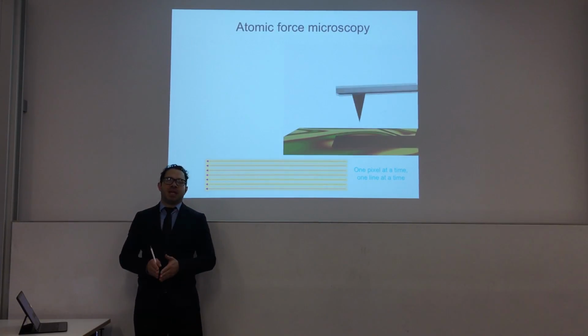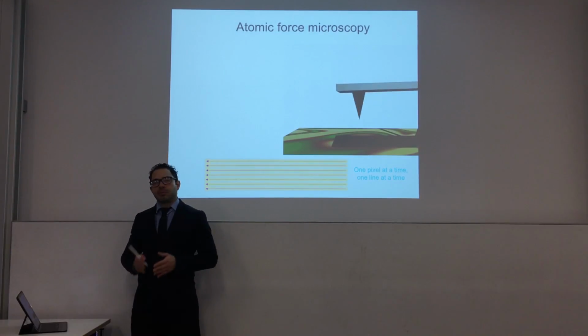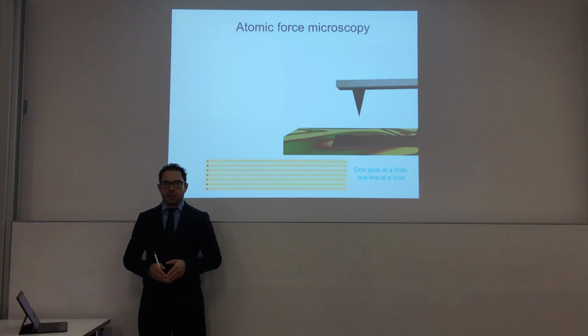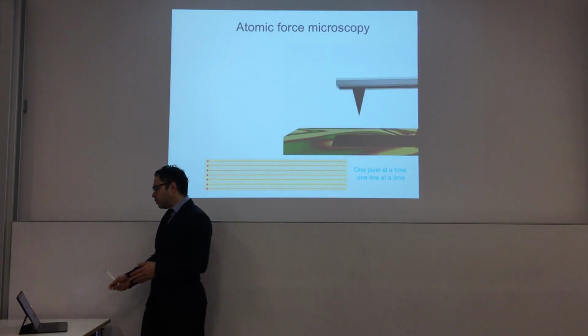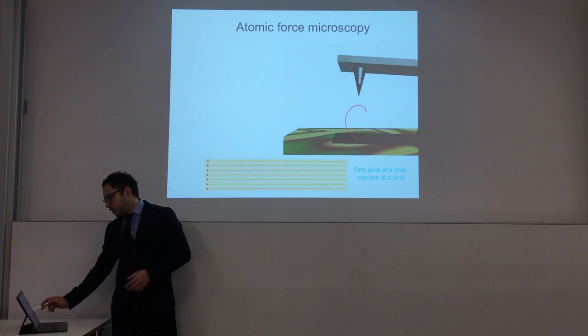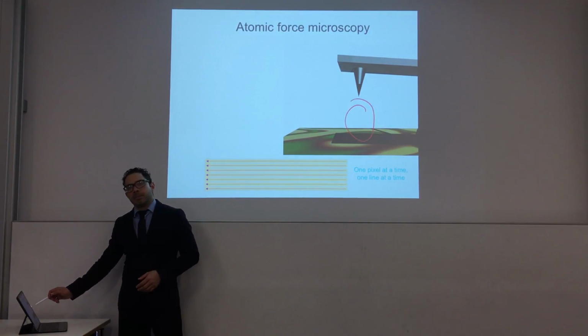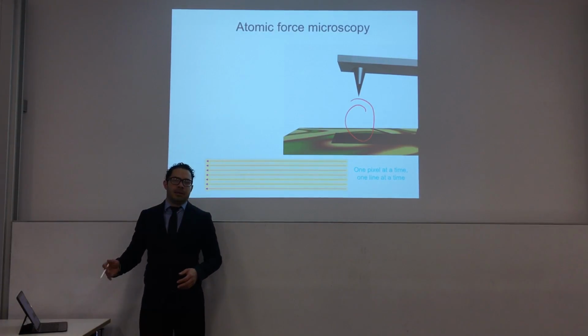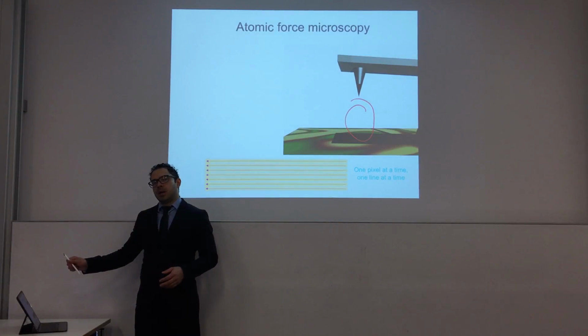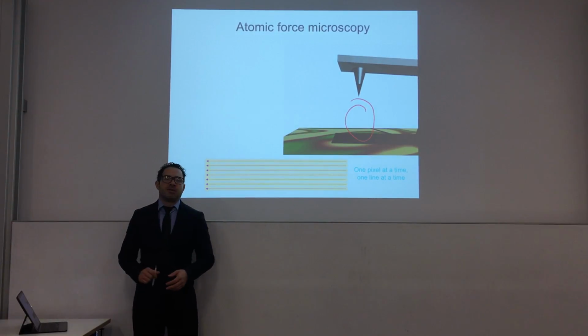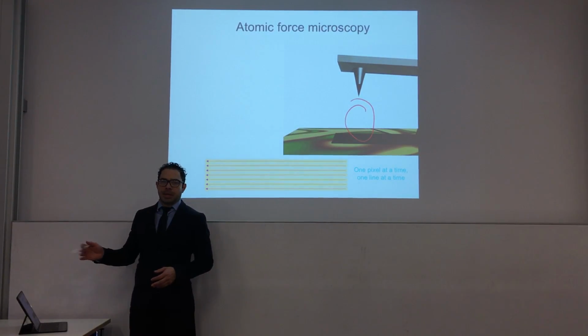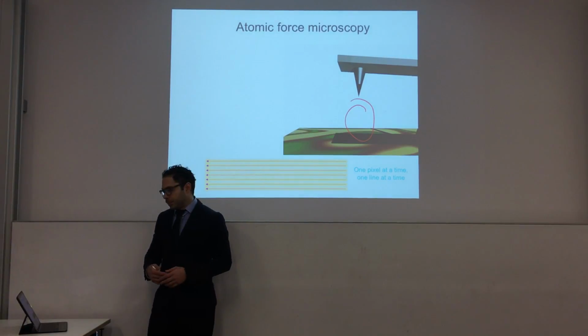You have a very sharp tip, but contrary to STM, you're not measuring currents. What you're measuring are interactions. So the interaction between the tip and the sample will be detected thanks to the force that it makes on the cantilever. The force on the tip will induce a deflection of the cantilever. So the cantilever in AFM is a force sensor.